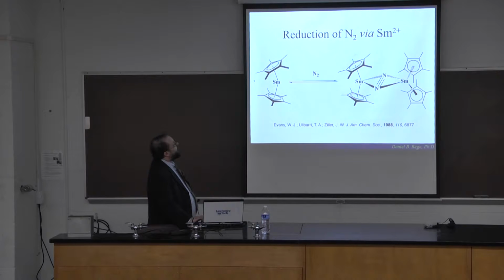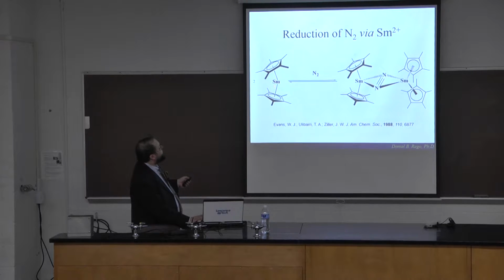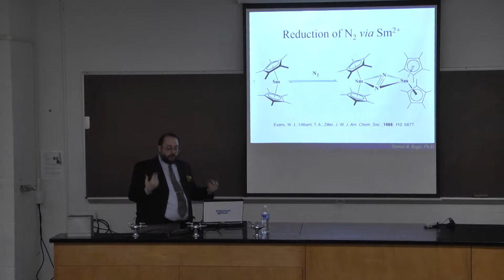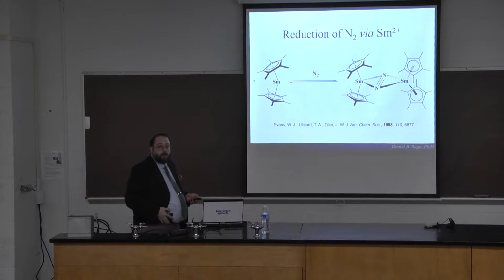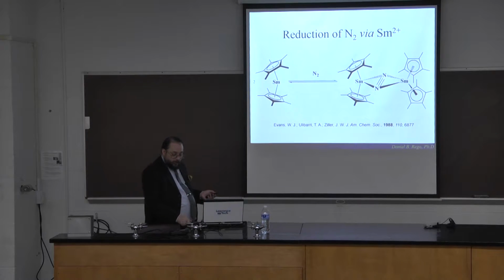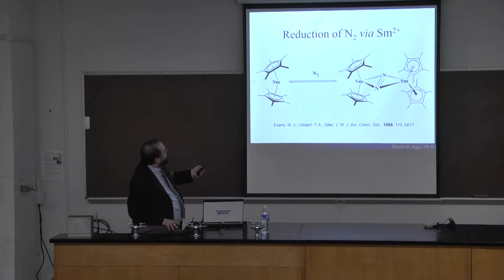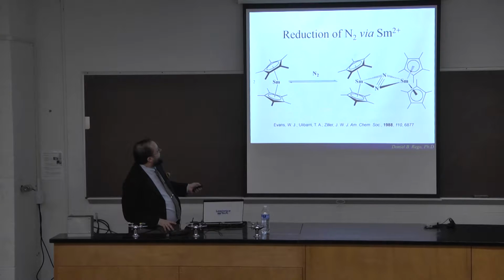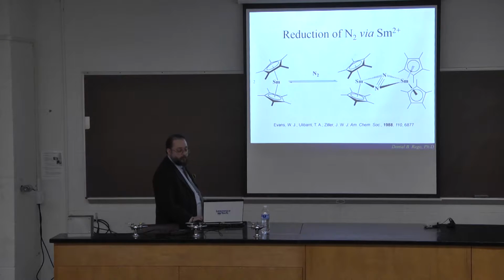So the first project I'd like to talk about is reduction of dinitrogen with lanthanides. This is a samarium-2 compound. So I said before that samarium-3 is the most common, but you can get divalent species, and this is one of the divalent species. Again, this is a bis(pentamethylcyclopentadienyl) compound. It turns out that this compound will reversibly bind dinitrogen, so as you lower the temperature, you end up getting more of this structure here. Now, if there was oxygen present, the oxygen would just immediately rip this to shreds, and that would be done with it. So this is a reaction done in an air-water free environment.